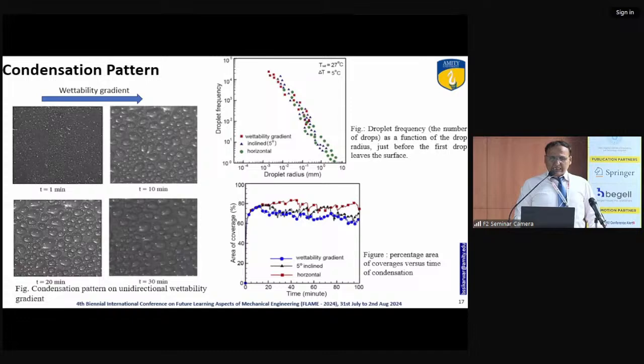These are the condensation patterns on a unidirectional wettability gradient. So you can see all the drops are shifted from the higher wettability sites. These are some experiments we have carried out on a wettability gradient surface, inclined 5 degree and horizontal wettability gradient surface. So you see the droplet radius versus droplet frequency. Here you see that the wettability gradient has a small droplet radius and a higher droplet frequency as compared to the inclined and horizontal surface.